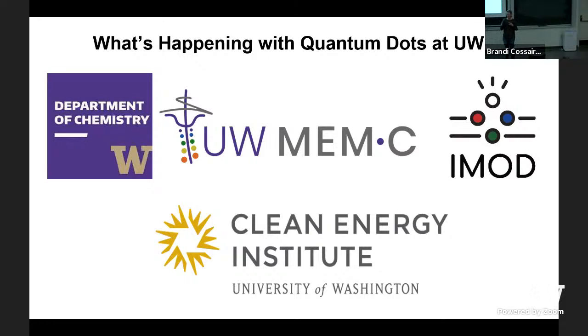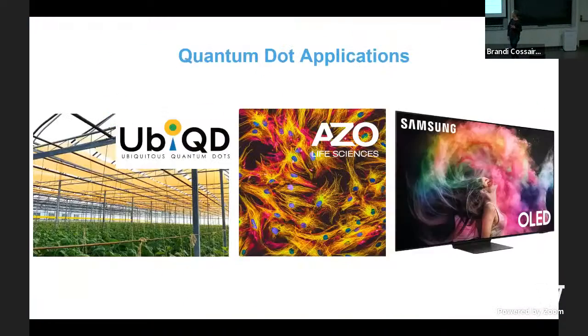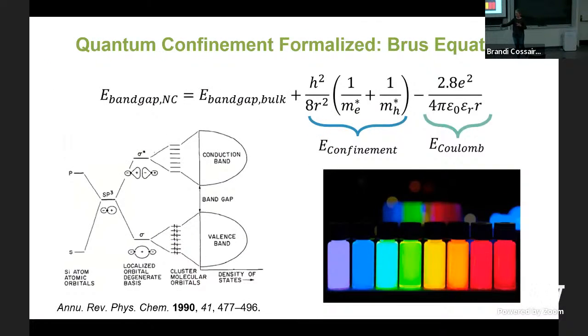So when you take a material and you confine the excited electrons and holes in the material below the length scale at which the electron and the hole naturally move around each other, you force those carriers into a box, which increases their energy. And so as you make the box smaller and smaller, the gap in energy between your filled orbitals and your empty orbitals starts to increase. As you make the box smaller, that wave function is more and more squished, and that leads to higher band gaps. So you move from your bulk band gap, which might be in the red, to your very strongly confined band gap, which is in the blue. Is that clearer?